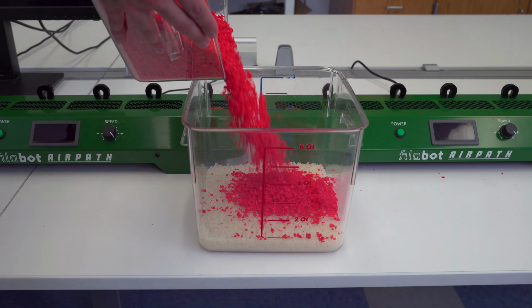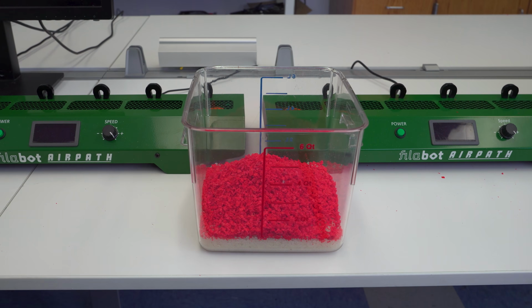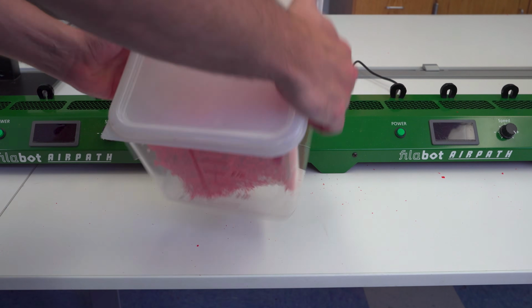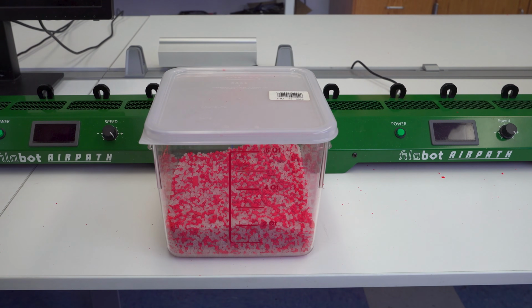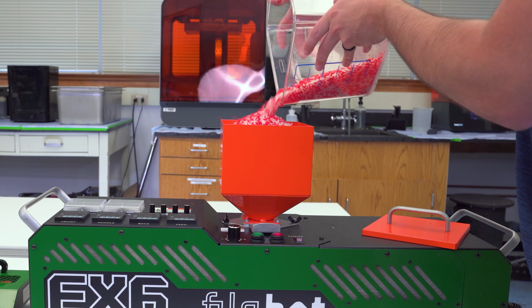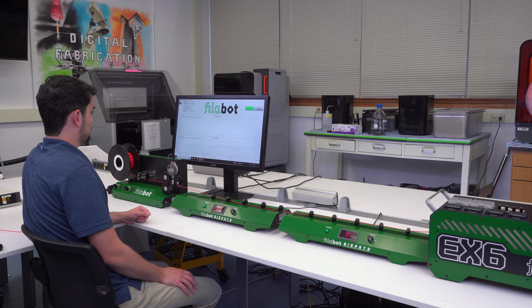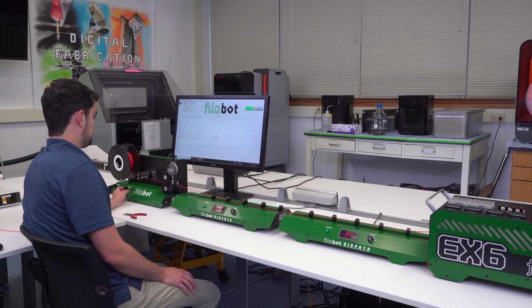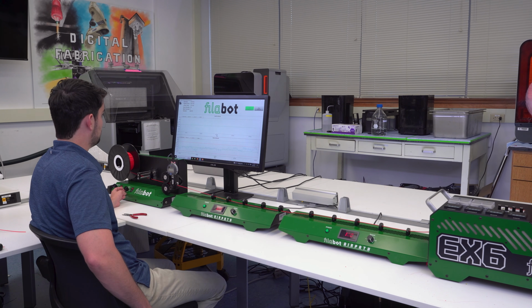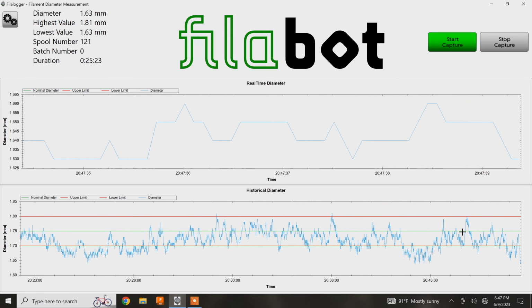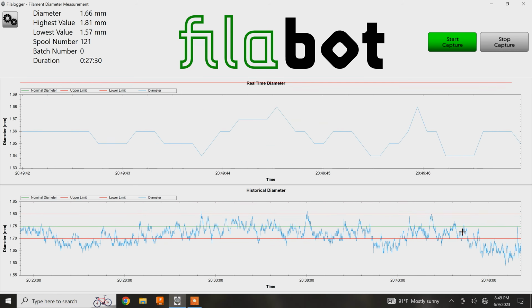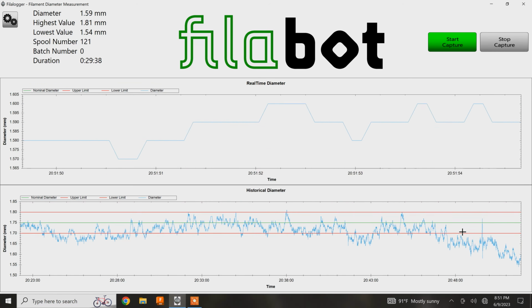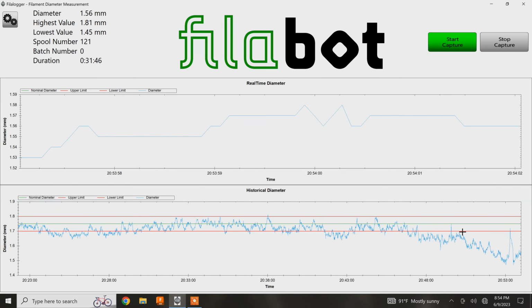To demonstrate this problem, I created two different ratios of regrind to pellets. First, I have 25 weight percent regrind, with the other 75% of the mass being pellets. I was able to spool the filament, but I needed to constantly adjust the drive wheel speed. I had a small amount of success in the beginning with keeping the filament diameter within the plus minus 50 micron lines, but eventually the output was so variable I could not change the speed fast enough.